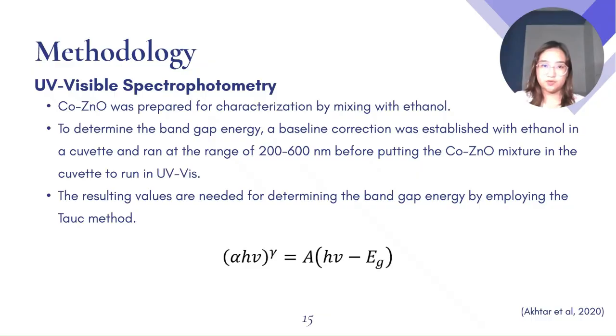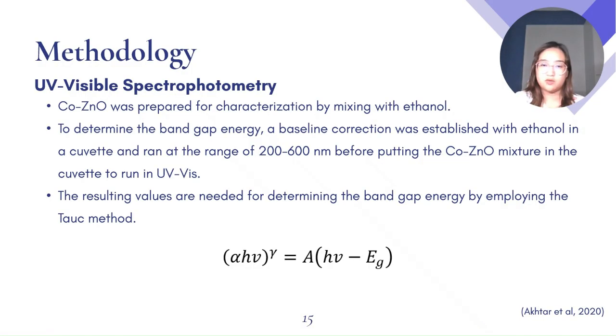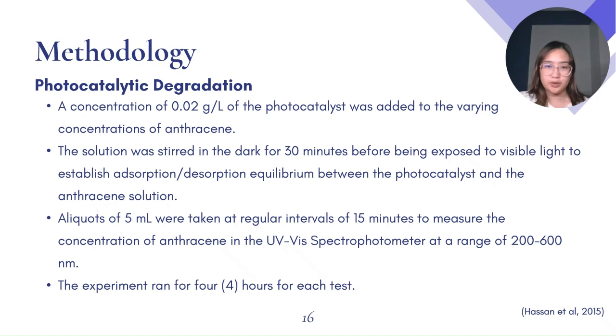In the utilization of UV spectrophotometry in characterizing, Co-ZnO was mixed with ethanol and run at a range of 200 to 600 nanometers. The blank solution used was ethanol. The bandgap energy was calculated using the Tauc method, and the formula used is the following equation from Akhtar et al. 2020. To evaluate the photocatalytic degradation of anthracene, UV-Vis was also used.